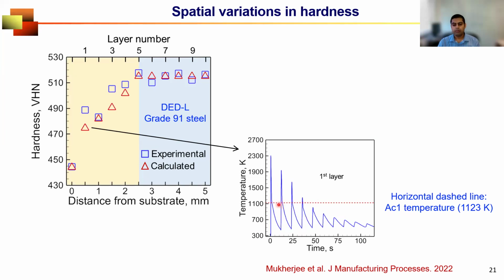But you see, for this case, for the first 4 cycles, whatever martensite forms goes back to austenite because the temperature goes beyond 1100 Kelvin. But after some time, the peak temperature is not going beyond the AC1 temperature, and whatever martensite forms undergoes repeated heating and cooling, and that martensite transforms into tempered martensite. So that's why the hardness is less than the top region.